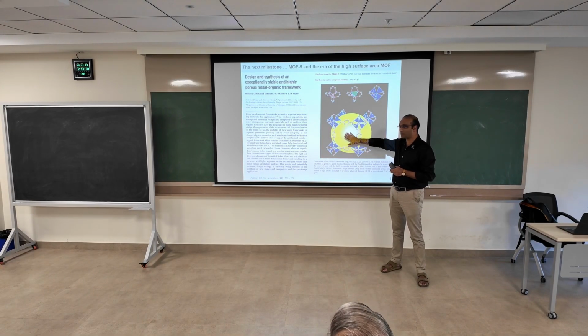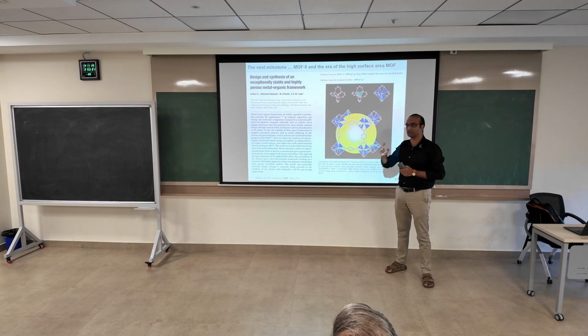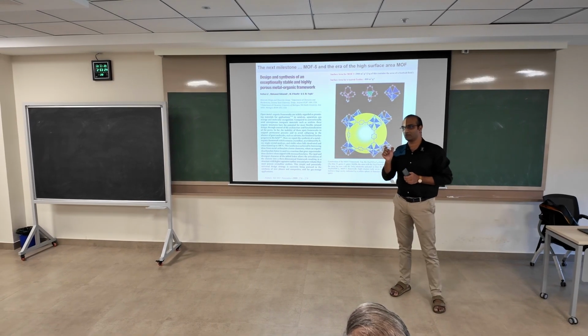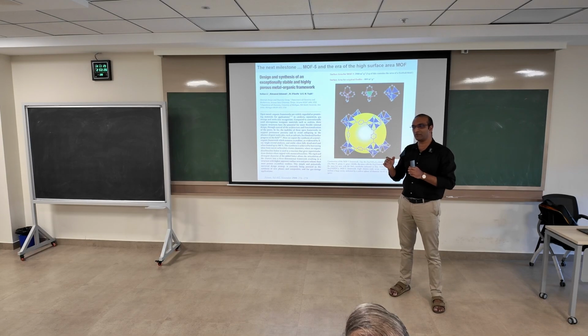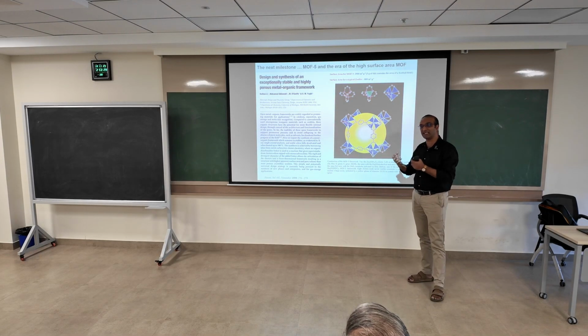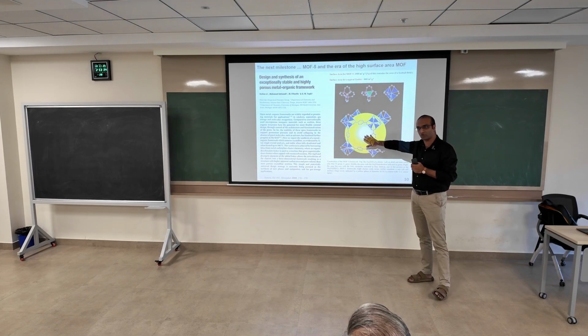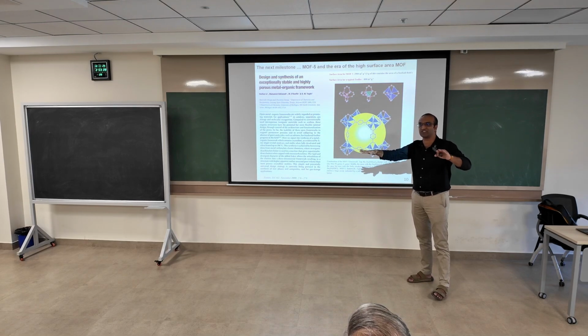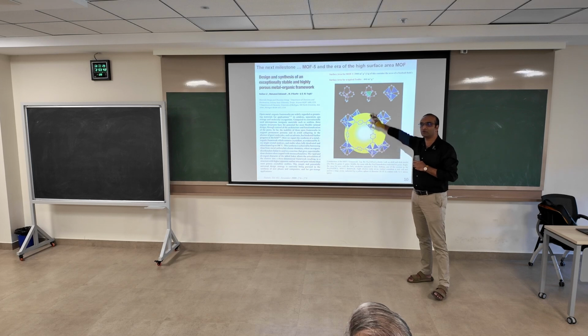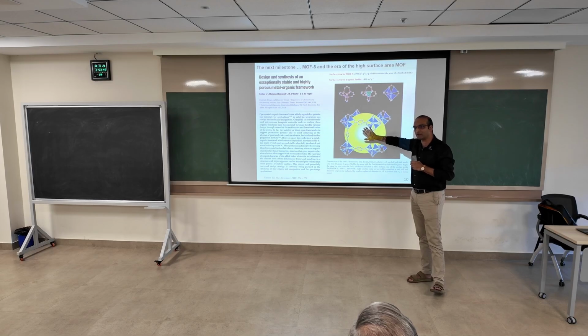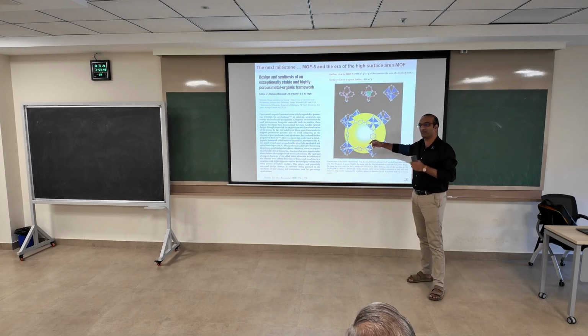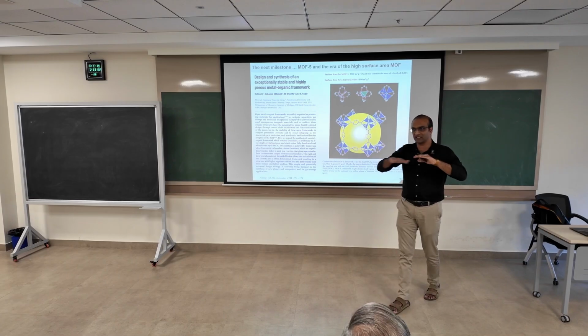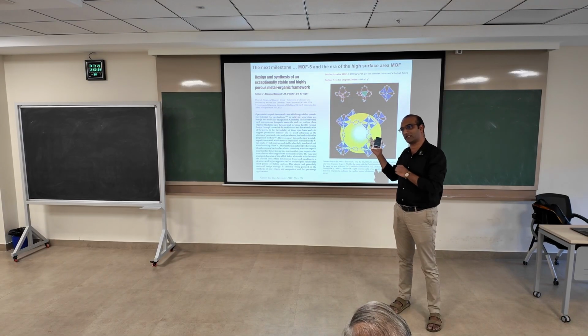So I'll tell you what we do generally for most porous materials: we use a technique called N2 physisorption. It's called BET. It's an instrument where you put gas into these materials and see how much gas they take. We usually assume it's monolayer adsorption, though it's obviously not monolayer adsorption. But we use that number to say that this would be the surface area, as a monolayer adsorption would be equal to that much. So typically to determine the surface area of these things, we fill the volume with gas and then assume that it's forming a monolayer and use that to translate into the surface area.